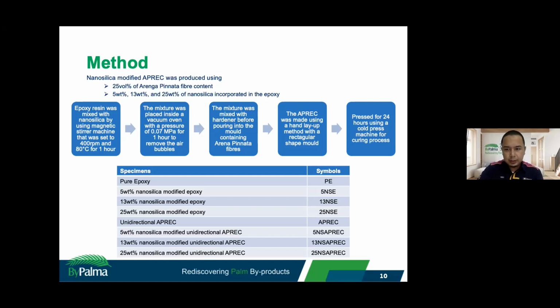A magnetic stirrer machine was set to 400 RPM and 80 degrees C for 1 hour. Then we place the mixture inside a vacuum oven with a pressure of 0.07 megapascal for 1 hour. The function is to remove the air bubbles. Next, we mix the mixture with hardener before pouring into the mold containing Arenga Pinnata fibers.